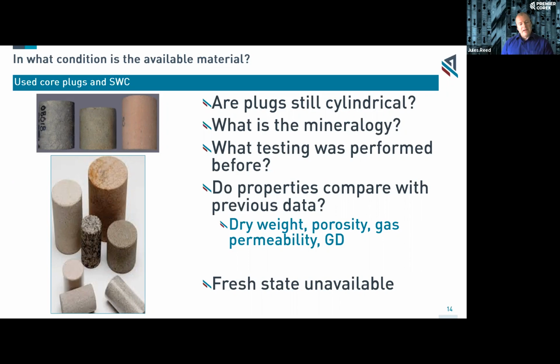Now, these previously used core plugs are potentially better than an outcrop block, as long as you've done the due diligence of ensuring that the properties are similar. Quite often, used core plugs can be used over and over again, and it's one of the beauties of analysis with clean state or restored state analysis. You can take a plug, clean it, saturate it, measure the properties, then re-clean it, saturate and measure the properties, and each time it should be consistent.